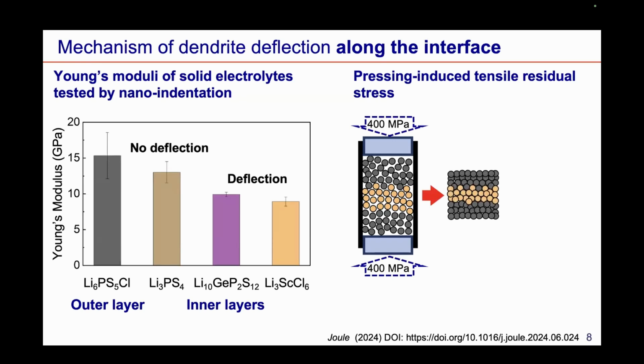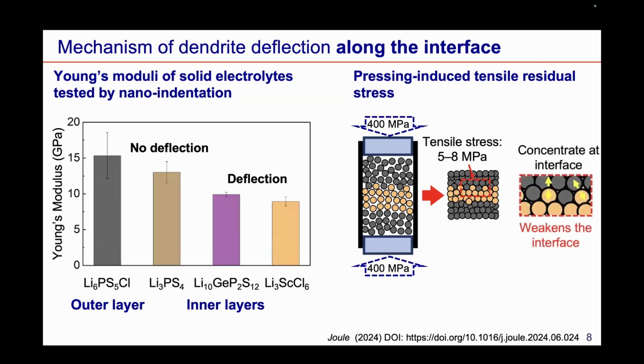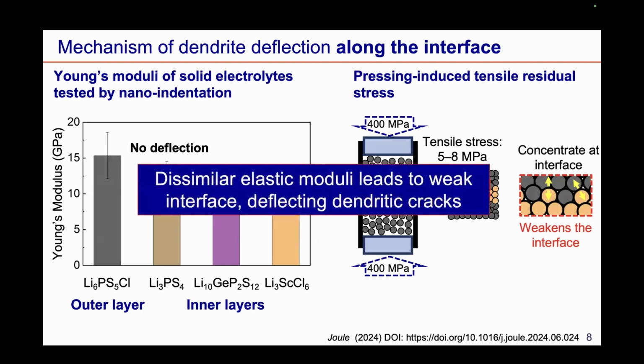After releasing this pressure, synchrotron XRD detects a residual tensile stress of 5 to 8 megapascals around the interface between the layers. This tensile stress will concentrate at the interface between the layers which exhibit dissimilar elastic moduli. And the tensile stress perpendicular to the interface will weaken the interfacial bonding. So compared to the bulk materials, this weakened interface may be more susceptible to fracture when a crack approaches this interface. Thus, this deflects the dendritic crack. So we can conclude that it is the dissimilar elastic moduli between the different layers that lead to the weak interfaces where the crack will deflect.